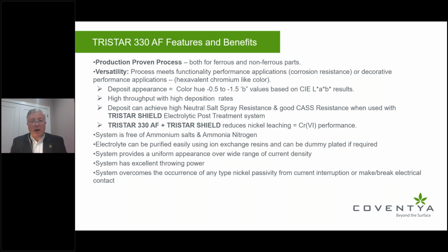And that's important. We have high throughput, high deposition rates. You'll see again a difference in what we target for functional application versus decorative. We can achieve very high neutral salt spray resistance today and good CASS resistance when we incorporate the use of the Tristar Shield electrolytic post-treatment system. And so one of the other elements that are important today is people are looking at nickel leaching, or the leaching of nickel layers, in a lot of different applications. And with Tristar 330AF and the Tristar Shield, we can show, and we've demonstrated, that we equal Chrome 6 from the standpoint of the reduction of leaching of nickel from these coatings.